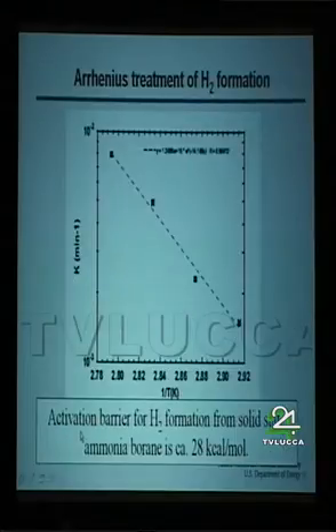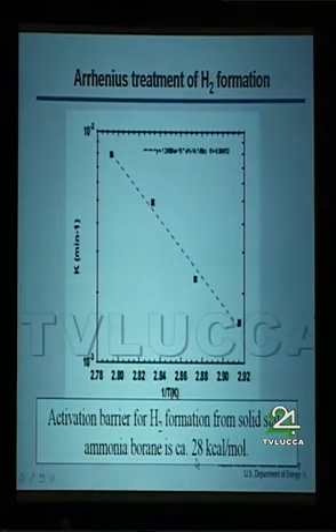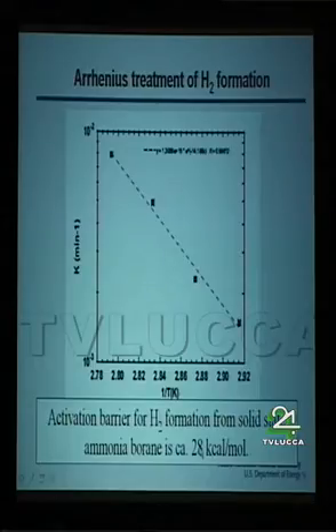But now we have these rates as a function of temperature. We can get an activation barrier. You do an Arrhenius treatment of this data, and it turns out that the barrier for release of hydrogen from this is about 28 kcal per mole. But you have to remember, this is the rate limiting step here.